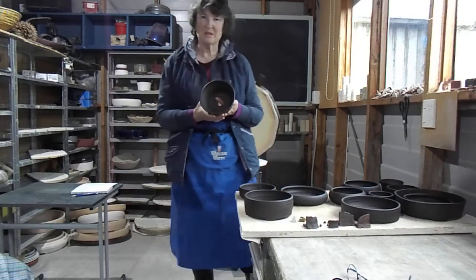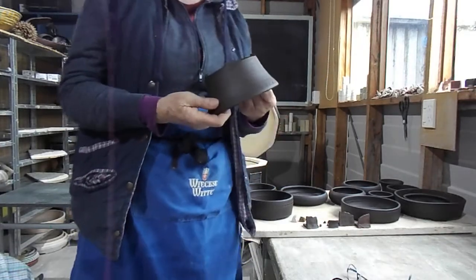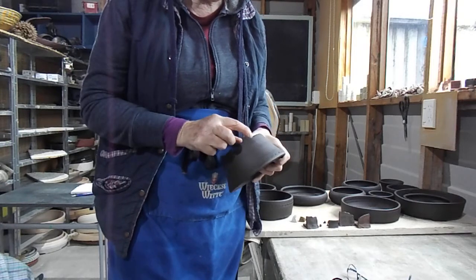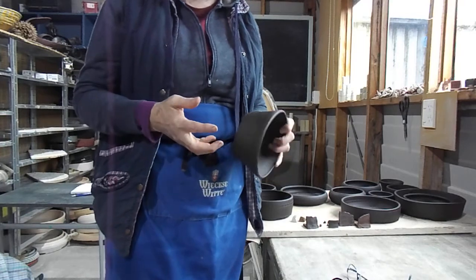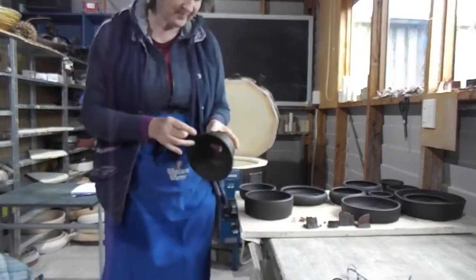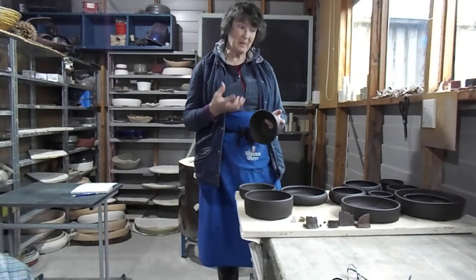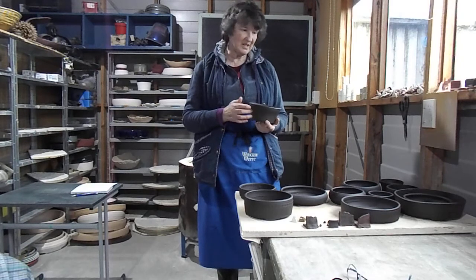It's really disappointing after all this work that I've put in. You can see little bubbles here and there — they look like air bubbles. They're just bubbles that were full of gas, and sometimes when you over fire pots that will happen. These are on the edge of starting to melt or bubbling anyway. I knew I was pushing it a bit much but I wanted this nice dark colour.